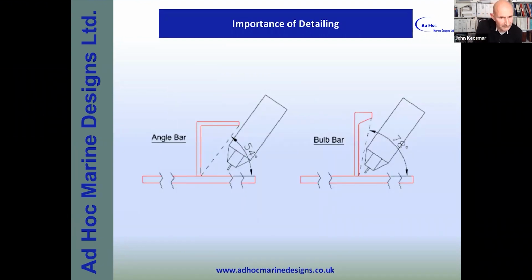And then if we go down even further, to the type of shapes that you're choosing for stiffening, we can see here on the left, the angle bar. If you take an angle from where the web butts into the plate, the subtending angle is 54 degrees. And even still at that angle, the torch cannot actually get inside. Whereas in the bulb bar, even though it's 78 degrees, the torch can quite easily get into the inside of the web of that bulb bar. So clearly with the angle bar, the welder, as he rotates his torch to try and weld the inner face, is not going to get a very good quality weld.